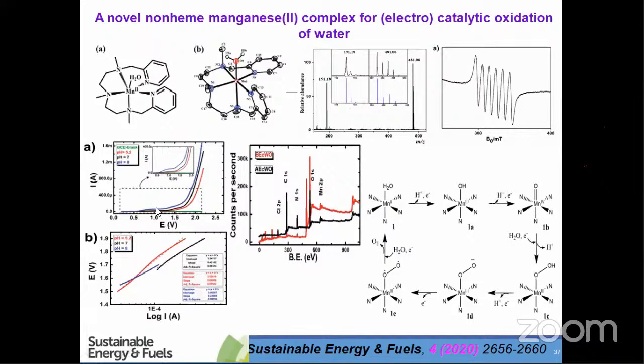You can see here the onset potentials at different pHs were different. From the Tafel plot and other data we could propose this mechanism for water oxidation, right? Before and after water oxidation, whether the manganese compound exists in solution or not was checked by XPS data. And this work was recently published in Sustainable Energy & Fuels.